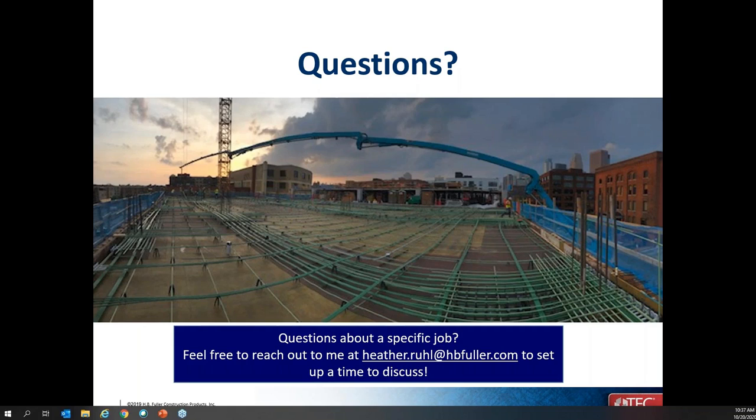Yeah, so that is a fantastic question. There's two parts of the different types of cracks that you want to be aware of. First off, there's a difference between dormant cracks, which I believe is what you're asking about, and expansion joints. So make sure that you know, is there any movement happening with the joint? If there is, it of course needs to be honored throughout the entire installation. For the expansion joints, at least, typically what we'll recommend is that you make sure you coat the entire interior of the expansion joint and then fill it with backer rod. And then when you pour your self-leveler or when you put patch over it, you honor that expansion joint throughout the entire installation. And what you were asking about, I believe, which is the dormant cracks, typically what we're looking for is whether or not it's moving and how large it is, right? So if you've got a really small narrow crack, you want to make sure you remove any dirt, any debris, anything like that from there, because those can cause bonding issues specifically on those saw cut joints and cracks.